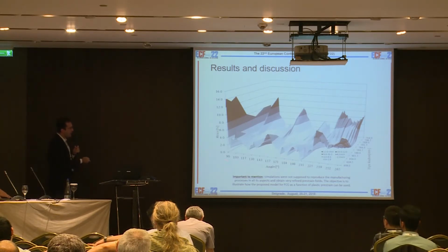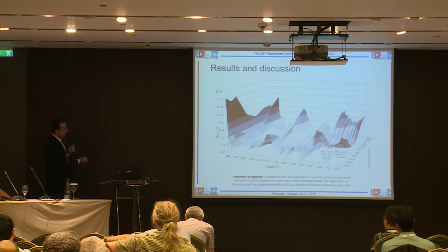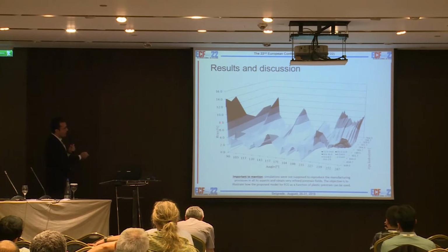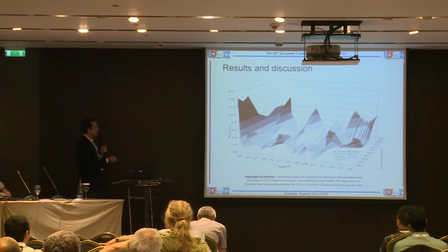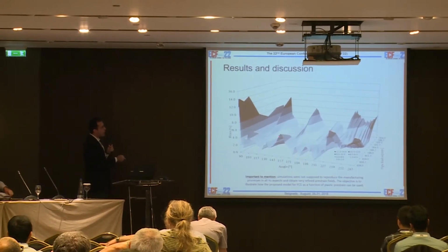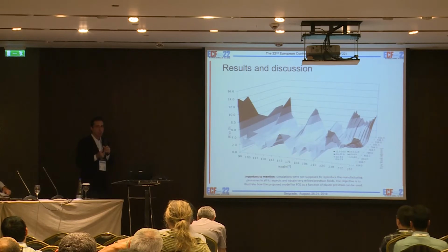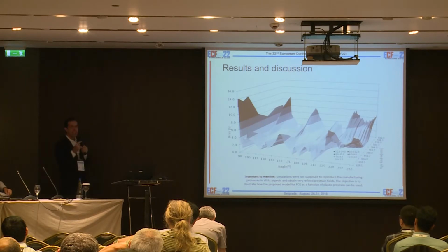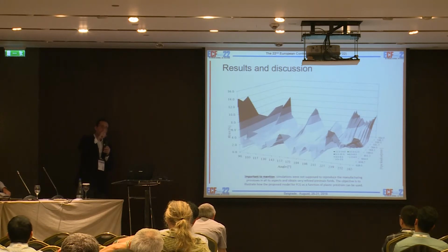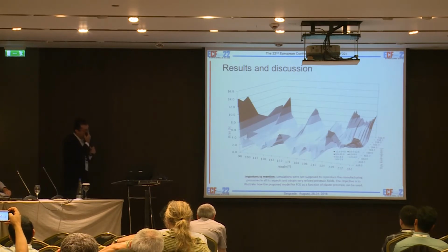So we can see here, for different angles in the pipe, the varying strain level in terms of percentage of prestrain for the different positions from the inside to the outside. And the neutral axis is in the middle. As we can see, the prestrain is not the same in different positions because the process is not continuous. So this is the critical one, that is the UOE. In calendaring, it's exactly the same along the pipe angles, but in UOE it's completely different, and it's usually employed for pipeline manufacturing.